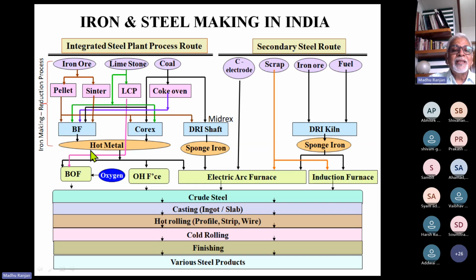The hot metal, which is the liquid iron produced from the blast furnace as well as the COREX smelting reduction process, becomes feed for the steel making process. The most dominant steel making processes are basic oxygen furnace and open hearth furnace. And if we look at the secondary route, we have electric arc furnace and induction furnaces, which act mostly as melting units. The iron making process is a reducing reaction process, and steel making is an oxidizing process. What we oxidize is the impurities. These impurities are oxidized and go into the slag, and therefore pure steel is produced. The steel can be further cast, hot rolled, cold rolled, color coated, etc. down the line.